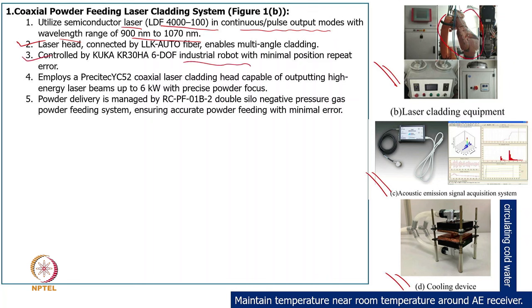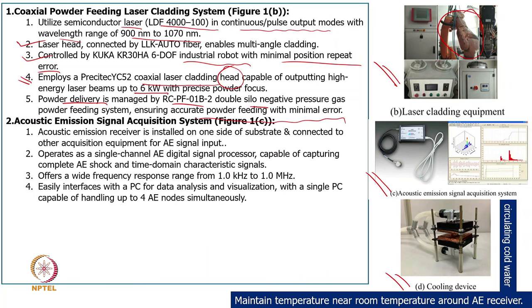You can see the industrial robot here, which has a minimal position repeat error to minimize error-related issues. And they use a coaxial laser cladding head, what we often call a nozzle, which delivers the powder. The laser was rated at 6 kilowatts with precision powder focus. Powder delivery is managed using negative pressure or some sort of suction pressure, so that accurate powder feeding is done with minimum error.